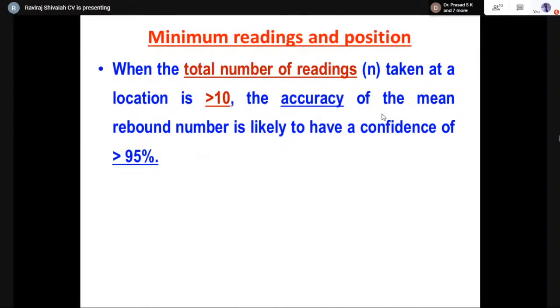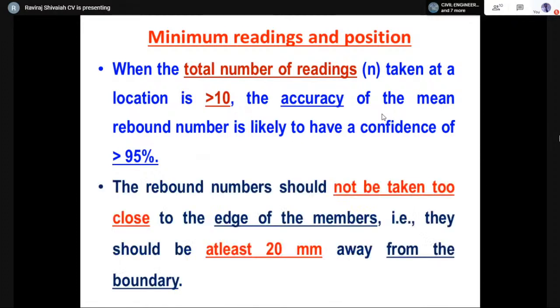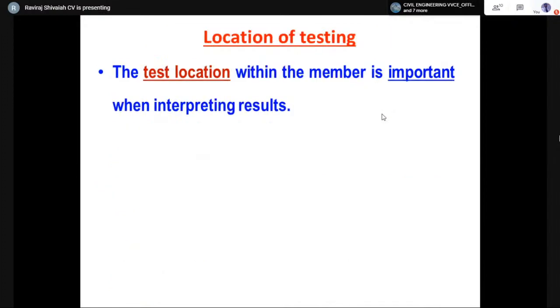And it's important to understand that we don't take only one rebound at a particular spot. If you try to do any testing, we always take many locations. We take readings at many important locations, and at each location where we do the test, we take more than 10 readings and take an average value of this, and record it as the rebound number at that particular location, correct? And when you do the test, you are not supposed to take the readings very close to the edge, and the distance between the readings should be at least 1 inch away from each other.